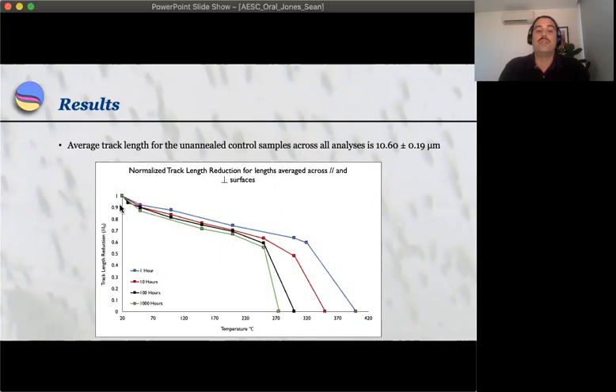The normalized lengths start at one, which is the control sample, and they reduce to about 0.5 or half the original length before dropping abruptly to zero by the next heating step.